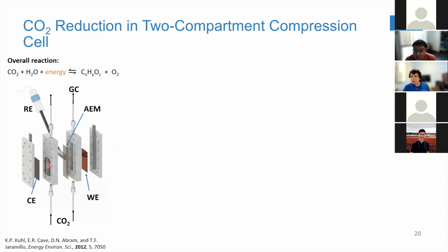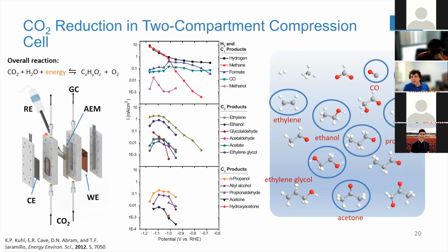Typically you have two compartments, a cathode where you make the fuel that you want. You have a membrane that prevents that fuel from coming to the anode, where you actually oxidize water to make oxygen. And if you do CO2 electrochemistry on copper, you see all these different products. We can see more than 16 different products from copper at the same potential.